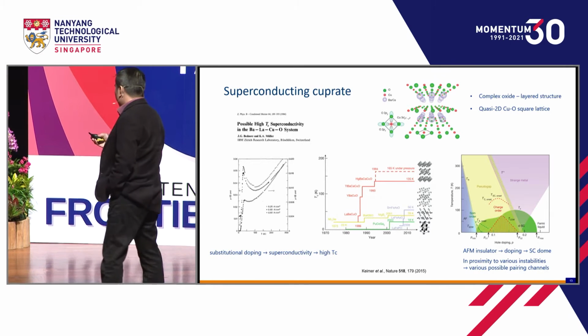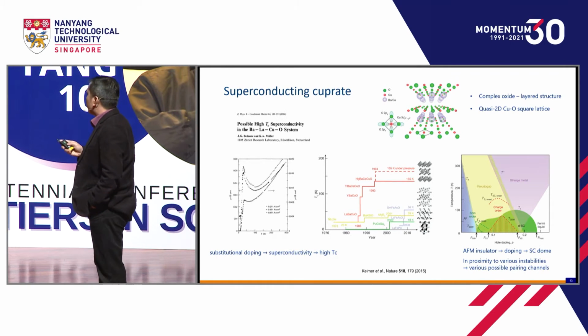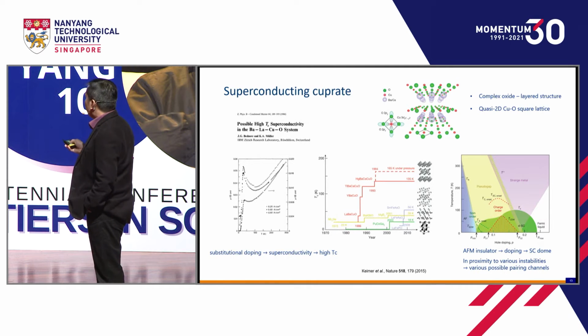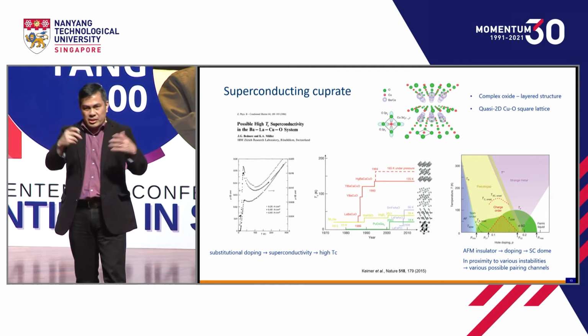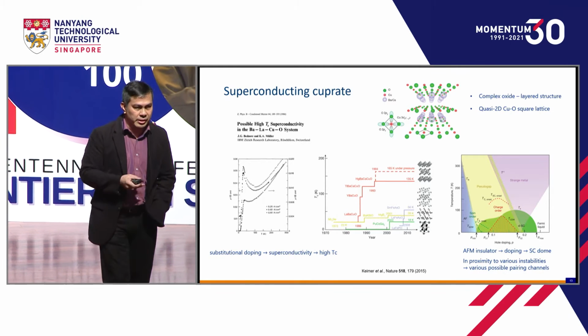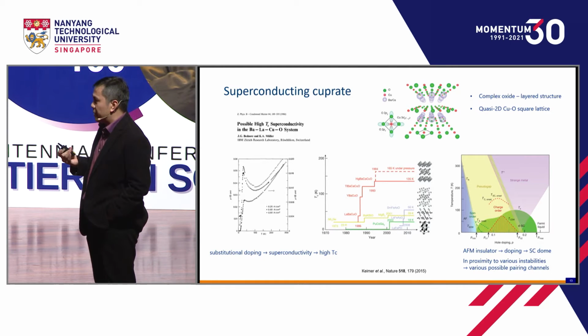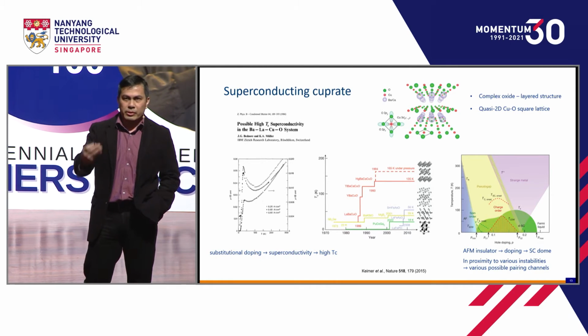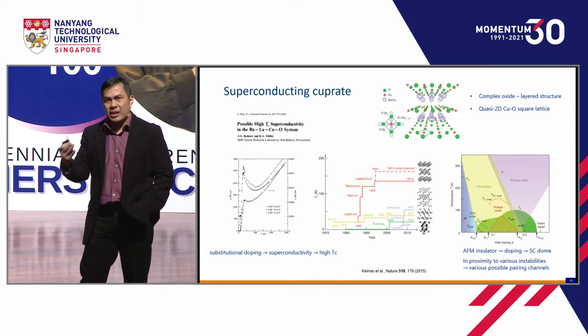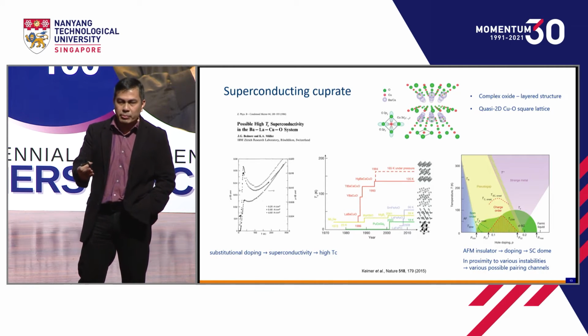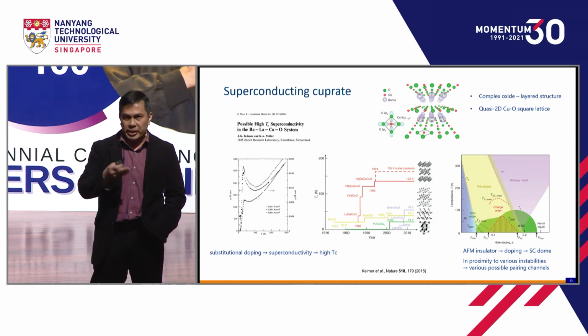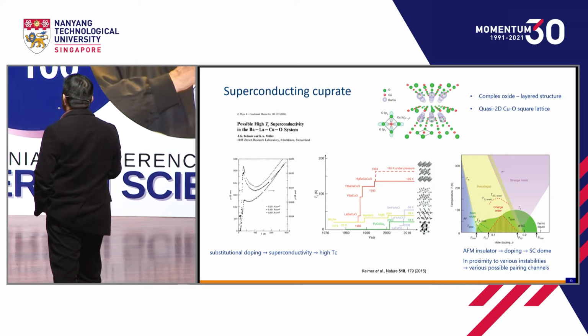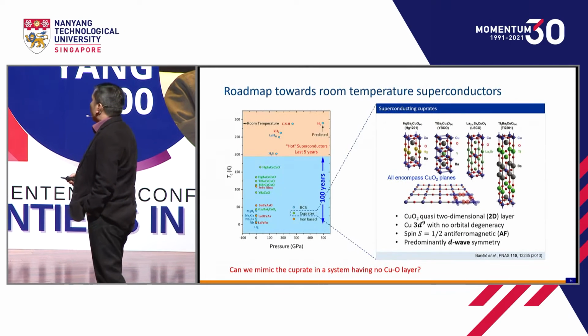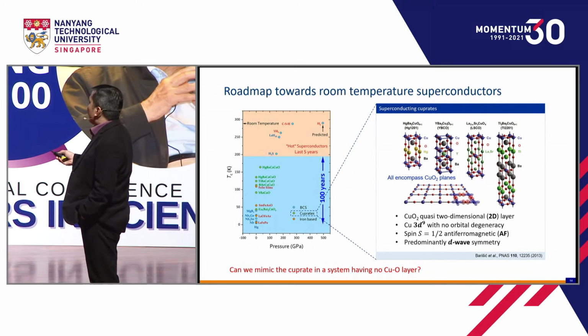Well, these are the basic features of the superconducting cuprate. When you dope the antiferromagnetic parent compound, it turns out to be superconducting within this superconducting dome. And in proximity, you have many different instabilities, like the charge density wave, spin density wave, heavy fermion, and so on. So this adds up to possible different mechanisms of the pairing, right? So it can no longer be based on the Cooper pair mediated by the phonon, okay? So this is a kind of roadmap up to now.